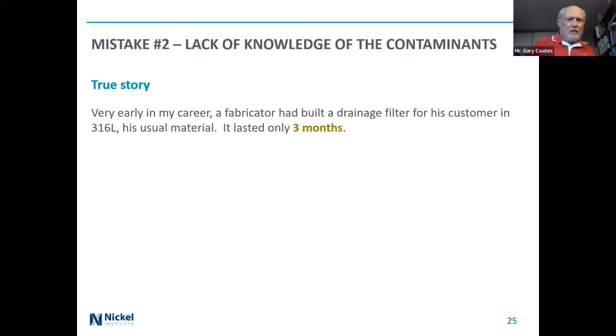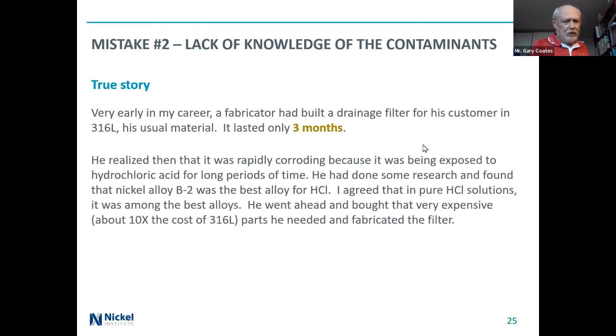So early in my career, a fabricator had built a drainage filter for his customer in 316L. What he usually built it in, it lasted only 3 months. He then went back and he realized that it was corroding because there was a lot of hydrochloric acid in what was going down the drain. He did his research and found that the nickel alloy B2 was the best alloy for hydrochloric acid, and I agreed that it was actually very good in pure hydrochloric acid solution. He went ahead, and it's a very expensive alloy, about 10 times the cost of 316L, and he fabricated the filter, and guess what? It lasted 3 days.